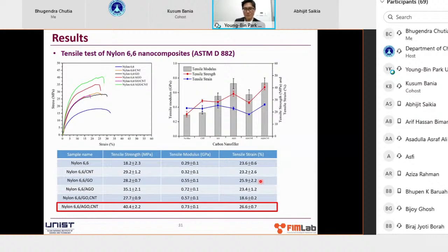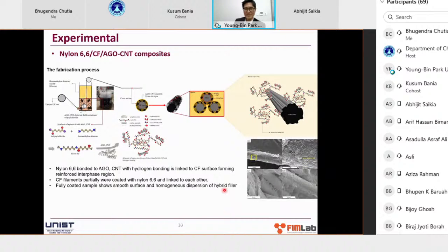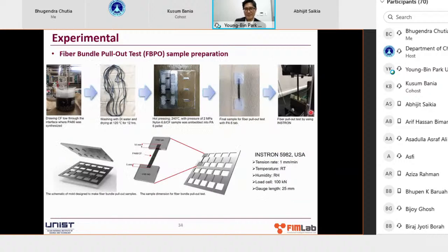So as a result, comparing with a conventional nylon, we were able to enhance the tensile strength, modulus, and strains. It's very difficult to enhance both the strength, modulus, and the strain, but in this case, we did that. And here, as I just explained to you, we passed a roving of carbon fibers through the organic solution, through the interface, and through the upper aqueous solution. And finally, we get a nicely coated carbon fiber with a sizing that contains the nanotubes and the graphene. So this is how we made the coatings and how we made the samples here.